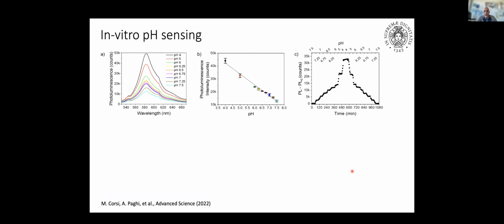And then here you see some of the in vitro results we get on pH sensing. You see the fluorescence is modulated with the pH level, and we have a very nice linear calibration curve over pH. I want to highlight that if you make a pH sensor with a single fluorophore, it allows you to monitor 1.5 points of pH. But in this case, we can easily go in a linear way from pH 4 to pH 7.5. This is because the fluorophore is not sensitive to the pH value itself. It's the polyelectrolyte multilayer which is sensitive to the pH.